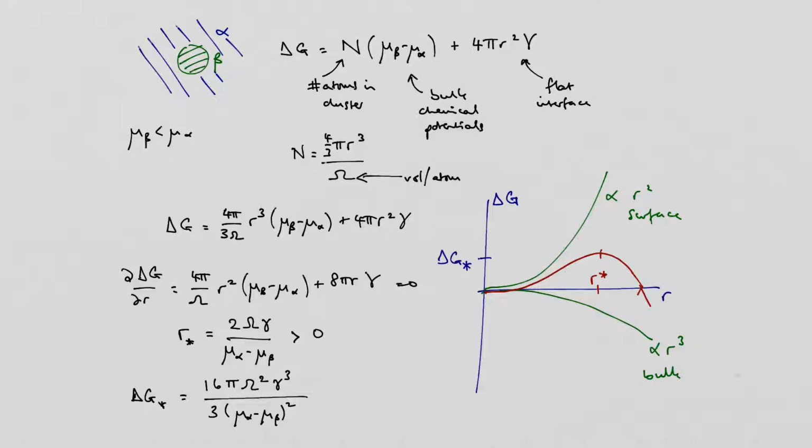And in fact, have you done Ostwald ripening? We discussed that. The larger ones will always grow at the expense of the smaller ones, because the larger you get, the smaller the ratio of surface area to volume. It's the volume energy that is driving this, and it's the surface energy that's costing you. So you have a system in which you have one big nucleus and one small nucleus.